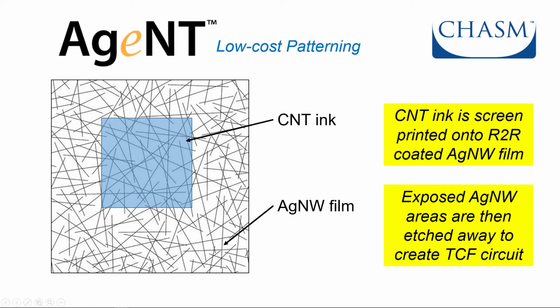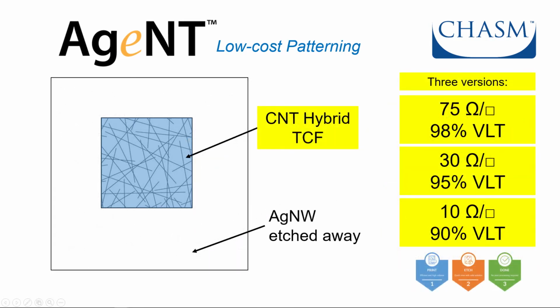And then we print any pattern that can be screen printed. We print carbon nanotube ink on top of that silver nanowire film. And then we etch away the exposed silver nanowires in seconds using ferric nitrate etchant. Print, etch, done. We have 3 versions of product, 75 ohm per square, 30 ohm per square, 10 ohm per